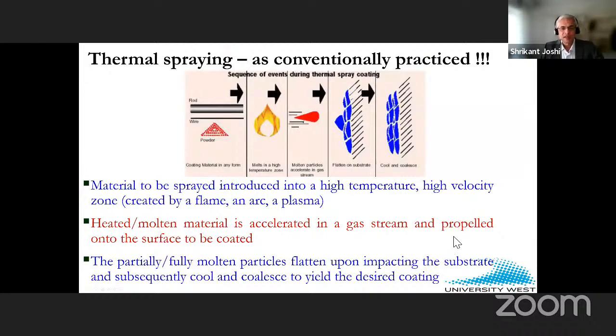Right. Let me then get to the theme of my talk. Please don't be scared by the slide that you see. I'm not going to get into the basics, but just to put liquid feedstock in perspective, and just in case there are new people in the audience, especially students: very quickly, how is thermal spraying conventionally practiced? You introduce a material from which you want to form a coating, sometimes in rod or wire form, but typically in the form of a powder. And the idea is to melt this material, accelerate it to a high enough velocity so that it forms splats, which are like pancakes on the part which is to be coated. And you overlap these splats to cover large areas, and you stack up these splats to build thickness, right? So typically that's how thermal spraying is practiced.